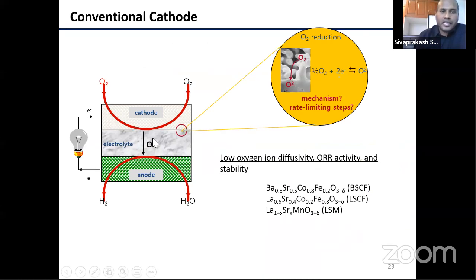In conventional cathodes, barium strontium cobalt ferrite (BSCF), LSCF, or LSM materials are used. The main disadvantage of conventional cathodes is that the oxygen reduction reaction is very sluggish or slow. Conventional fuel cells operate at 1000 degrees Celsius. When we decrease the operating temperature, this oxygen reduction reaction becomes very slow, and because of this, the overall efficiency of the fuel cell goes down.